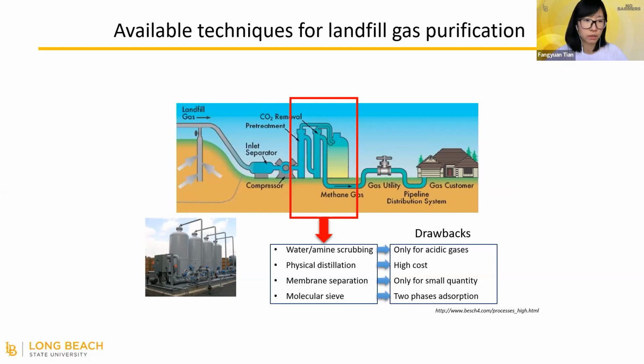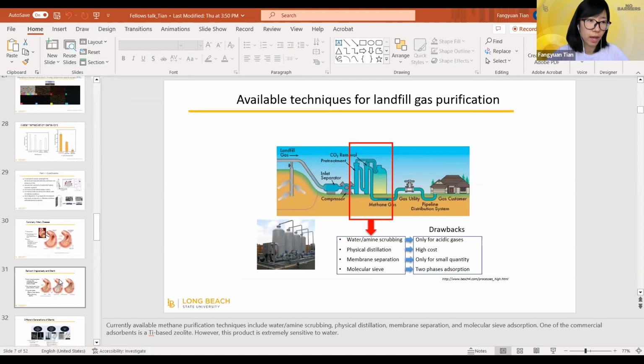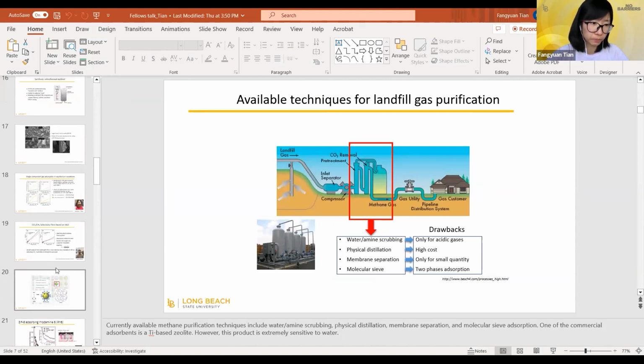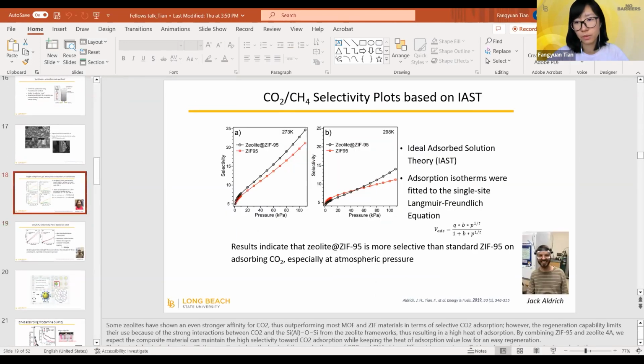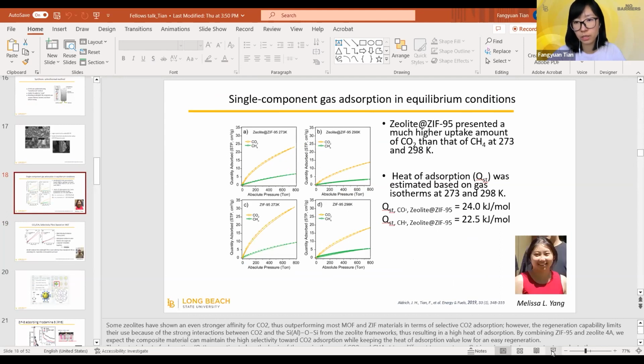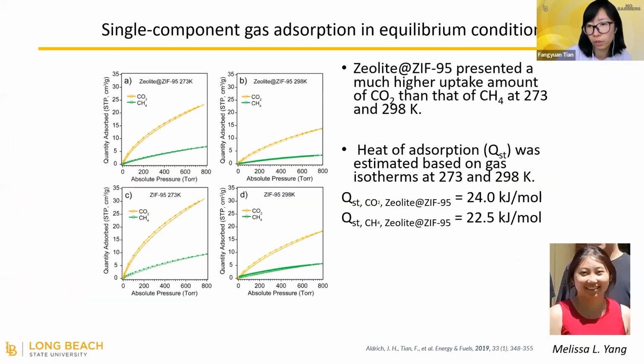And if you look at the QST value for our material, this QST value is relatively low for both carbon dioxide and methane. So you can just simply heat it up, and then the water will become vapor and leave the surface and the inside of the pores, and then you can reuse it.